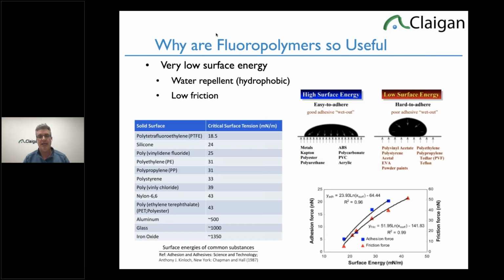So one of the things we talk about where it's used is, you have to understand why it's useful. Fluoropolymers are inert. They're very useful because they have low surface energy. Low surface energy on the surface of the material means it doesn't grip with other polar items. So water, it's very water repellent because water won't attach to it. The water is very polar, and PTFE has virtually no surface tension or energy, so it won't bind it. So this affects the friction. PTFE is incredibly water repellent. It's also oil and stain repellent. And because it has basically no surface energy, it has no friction. Friction is normally the surface energy: the two materials bind, they share electrons, and they grip. It's almost like small bonding. PTFE has none of that, so it just slips.